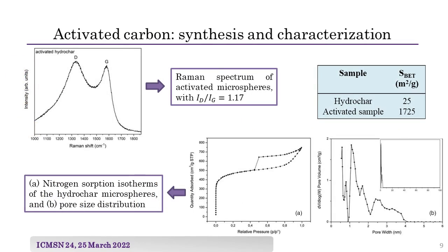The Raman spectra of the non-activated and activated sample show an increase in the D/G intensity ratio from 0.83 to 1.17. In graphitic materials, an increase in the ratio is usually interpreted as being due to an increased density of defects. However, in the case of chars, which are made of small clusters containing aromatic rings, the interpretation is opposite. It has been shown by Ferrari and Robertson that for crystallites with a lateral size lower than 20 angstrom, an increase in the D/G intensity ratio is related to an improved level of order.